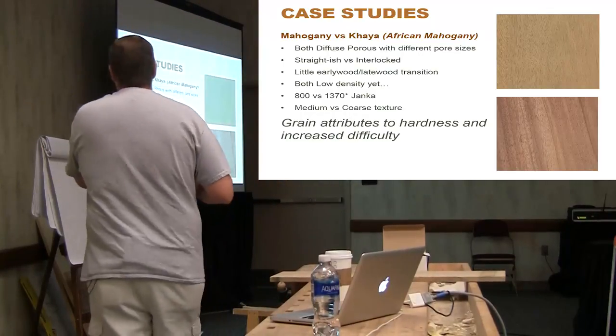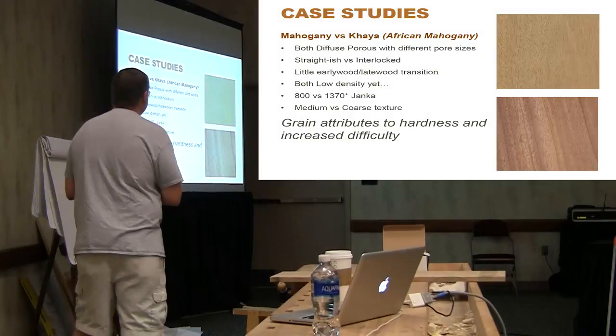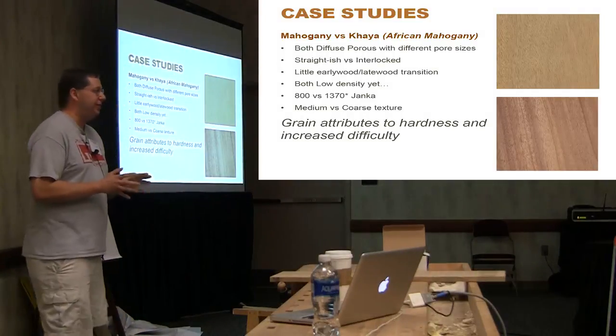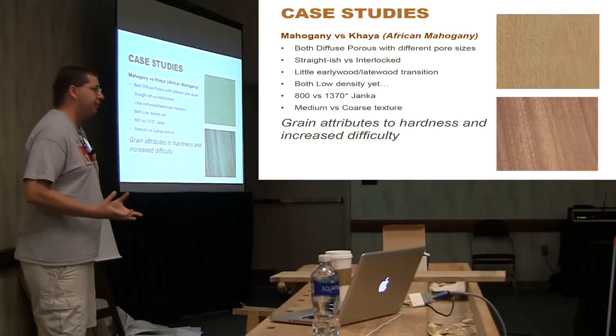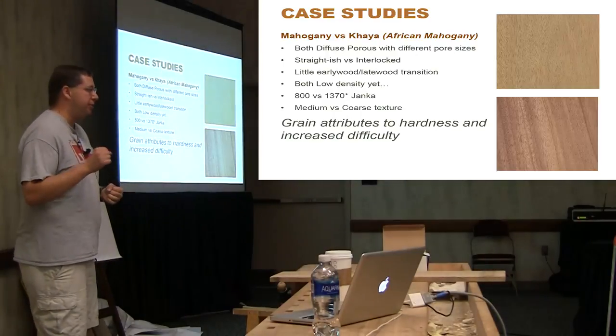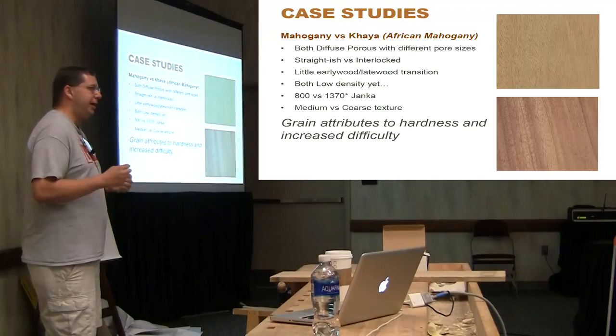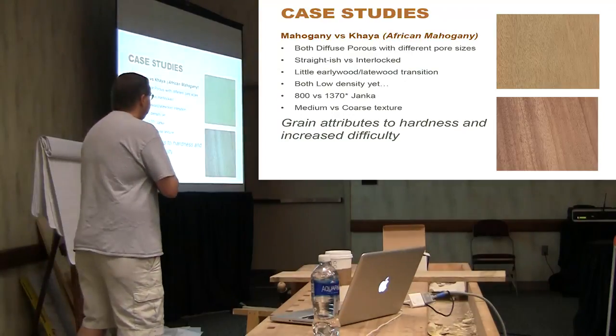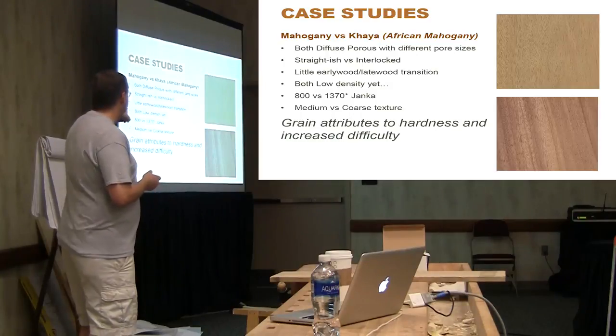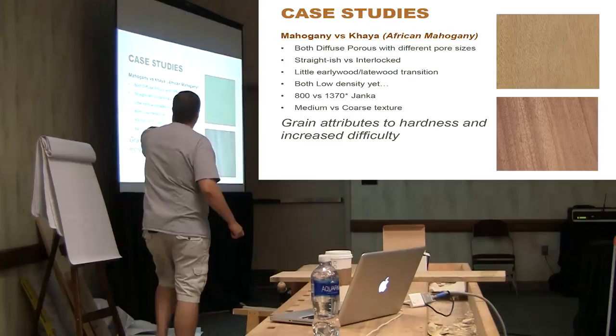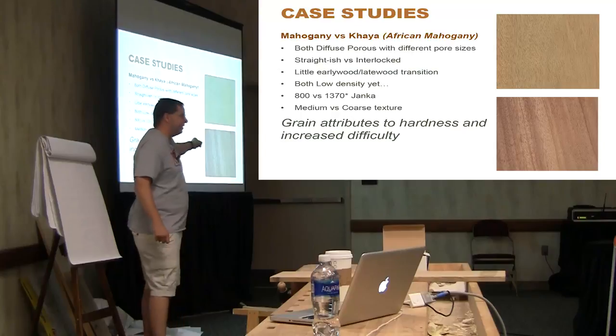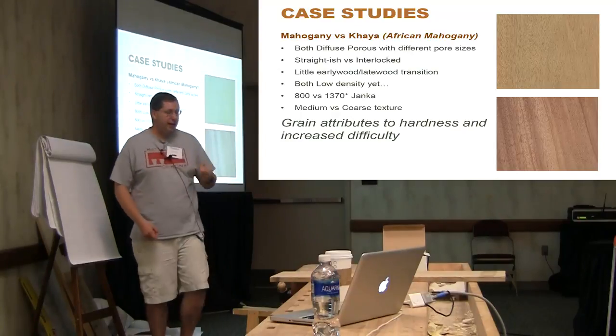So let's look at these. They are both diffuse porous, but they do have different pore sizes. So again, it's not just the ordering of those pores, but the size of those pores. Cherry and maple are a good example. Maple has smaller pores than cherry. Not that much smaller, but that may also help contribute to the extra hardness of that species. Here, mahogany has much bigger pores than Khaya. And you can see the density number, or the Janka numbers, down here. Our genuine mahogany, Swietenia macrophylla, is an 800 pounds-force rating versus 1370. It is because of that pore size.